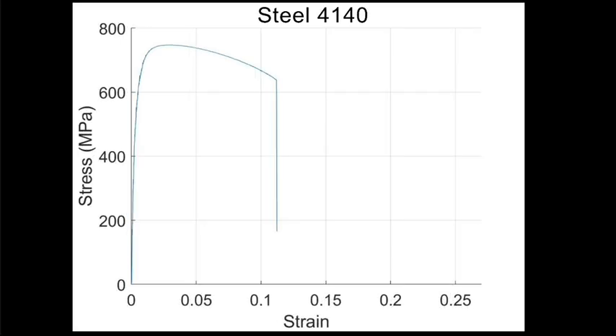In steel, we see it is a lot stiffer, so the yield point is a lot higher, being around 650 MPa. Due to its alloy composition, AISI 4140 exhibits a higher work hardening rate, meaning stress increases more significantly with further strain compared to aluminum or titanium.